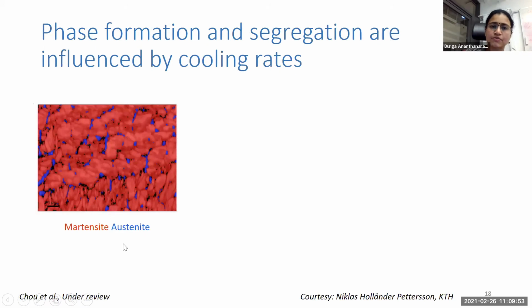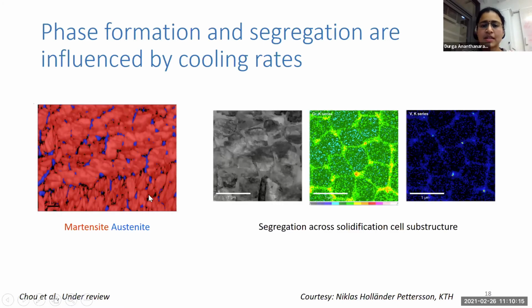What happens in the case of phases? So this is an example from steel, where at the end of the additive manufacturing process itself, we end up with a martensite and austenite structure, which is not what we have from, let's say, casting or other processes with lower cooling rates. So the cooling rate already influences the phases that form at the end of the process. And if we look inside the grains, they have this typical cell structure. And then across the cells, you have microsegregation that happens. So this is also an aspect that we need to take into account. For example, when we want to post-process this, heat treat it, then the level of this segregation would determine the temperature-time cycle that you would have to use for the heat treatment itself.